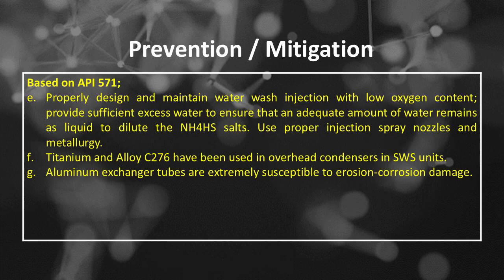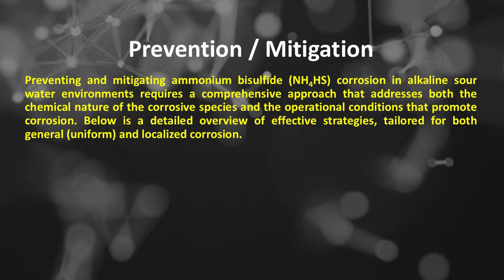Number G, aluminum exchanger tubes are extremely susceptible to erosion-corrosion damage. Preventing and mitigating ammonium bisulfide, NH4HS, corrosion in alkaline sour water environments requires a comprehensive approach that addresses both the chemical nature of the corrosive species and the operational conditions that promote corrosion. Below is a detailed overview of effective strategies, tailored for both general, uniform, and localized corrosion.